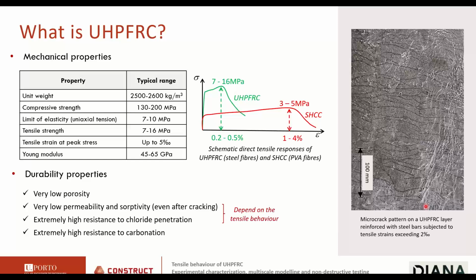Here in the picture, you see a very distinguishing feature of UHPFRC under tension, which is the ability to form a very dense network of micro cracks that sometimes we cannot see with the naked eye. So typically here what we do, we spray some alcohol and then the cracks reveal themselves while the alcohol is drying. And here you can see a UHPFRC layer subjected to tensile strains exceeding 2 per mil. You see a very dense array of cracks with spacings that can reach about 20 millimeters in this case.